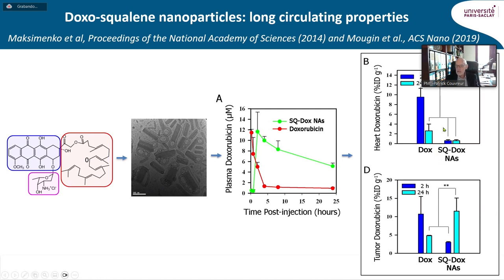as a free drug. And this will completely change also the overall biodistribution of the doxorubicin when administered as nanoparticles. You can see that you will be able to dramatically decrease the concentration of doxorubicin at the level of the heart tissue, comparatively here in blue to what happens after the administration of doxorubicin as a free drug. And this is very important because you know that the cardiac toxicity is the major limiting toxicity in the clinic of doxorubicin. Then also you can see that after intravenous administration of the squalene doxorubicin nanoparticles, you will be able to increase significantly the concentration of doxorubicin in the tumor comparatively to the free drug 24 hours after the administration.